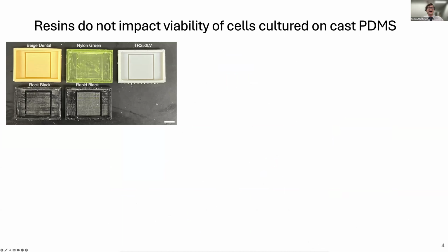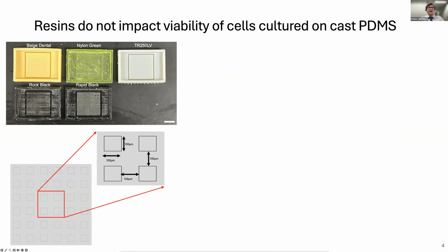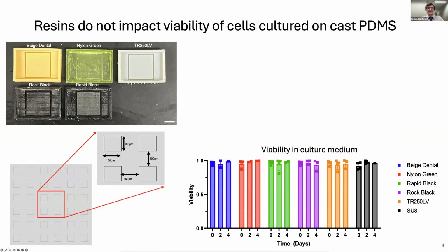Do they affect cell viability? To do this, we printed using 5 different resins. We printed a microwell geometry, cast PDMS, and then cultured cancer cells in the PDMS from these different molds. What we found was that the PDMS from these 5 different resins all had similar biocompatibility. We selected the TR250 LV resin because it had optimal thermal properties compared to the other resins.